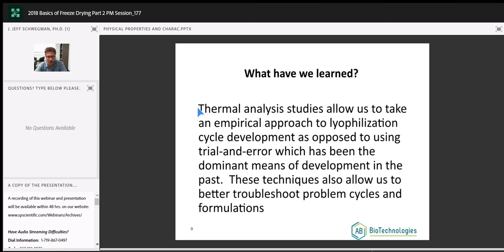So, for example, years ago when I was doing cycle development without this information, it may take us 15 or 20 pilot runs in a freeze dryer to get something that worked, and it probably wasn't optimized. By doing the thermal characterization, now when we develop a cycle for clients, we can do it in 3 runs. Develop a fully optimized cycle in 3 runs, and then we always do a confirmation run. So that's vastly different than what we used to do in the past, number one.